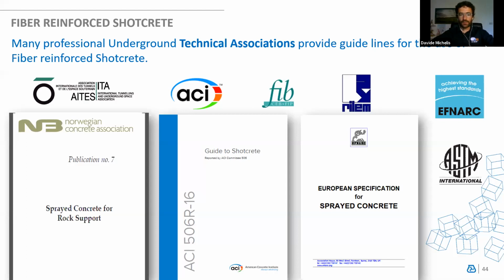Because when you spray the surface, and especially when you carry out tests on panels, as Mr. Jain has properly shown, it's needed to cast at least 3 panels for each test, for each curing time. Out of the 3 tests, the panels cast more or less at the same moment should have homogeneity in results. You cannot have a variation of 50% from one panel to another. Otherwise, it means that there is not a proper homogeneous distribution of the fibers inside the mix design.